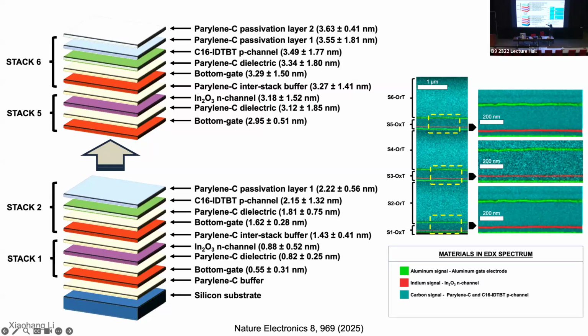So we started from less than 1 nanometer. And when we move up, you can see that the roughness started to move from less than 1 nanometer to 1+ nanometer, eventually to 3+ nanometer, right? So this indicates that we still need to do a lot of work in optimizing the whole fabrication process to reduce the interfacial roughness for the stacking. But nevertheless, we managed to stack 6 on the silicon substrate, right? Half NMOS and half PMOS.